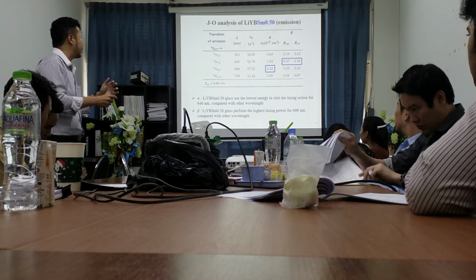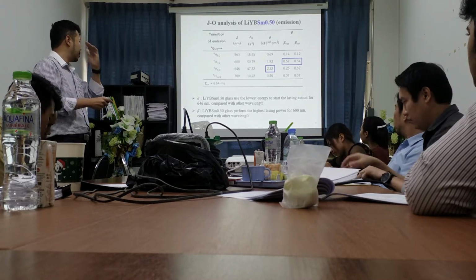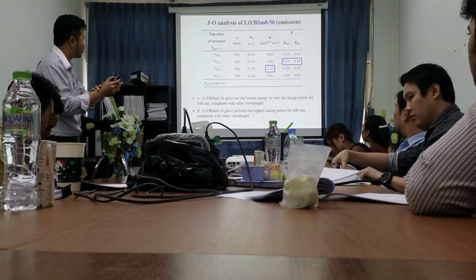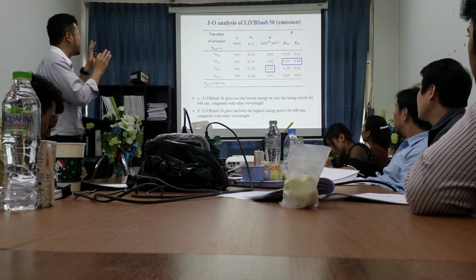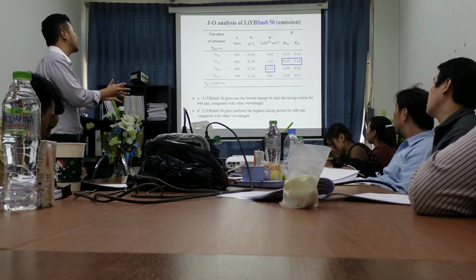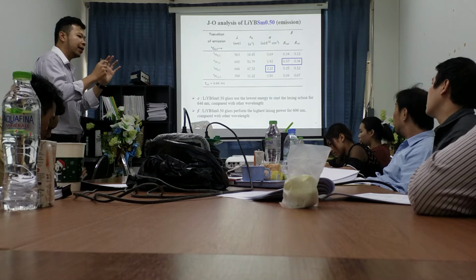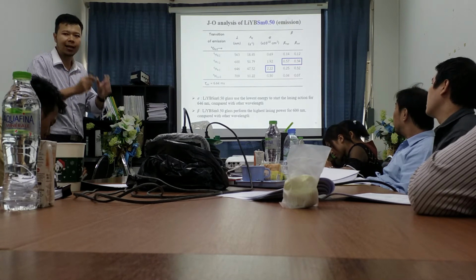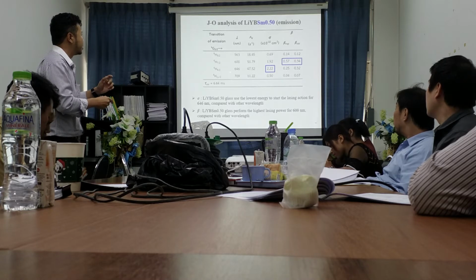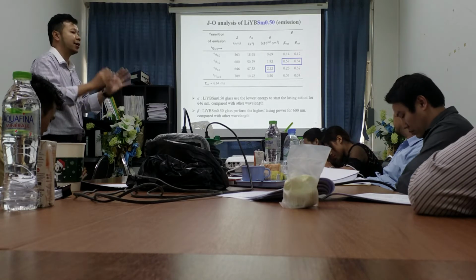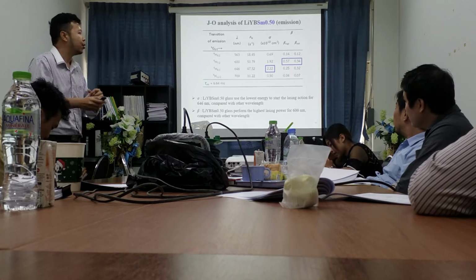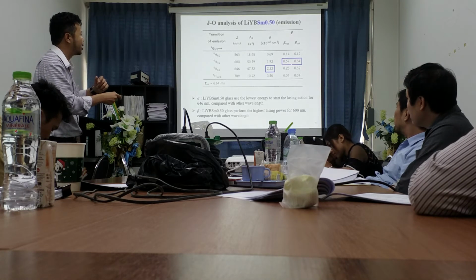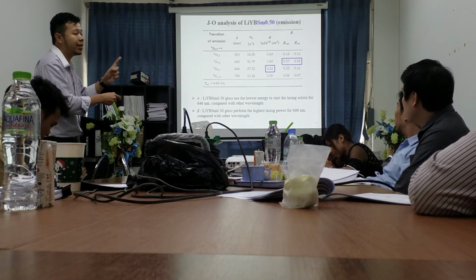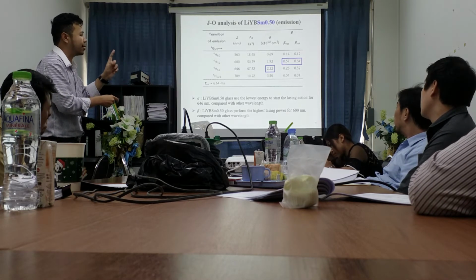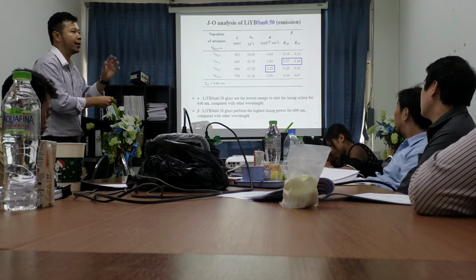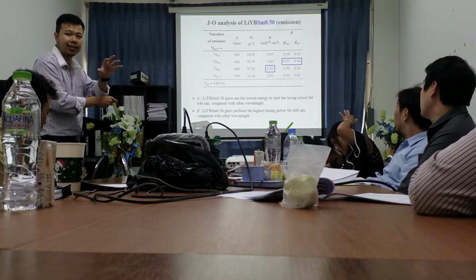The second step, we get the sigma and the beta, but we have a conflict between the sigma and beta values. From the discussion, we can say that if you want to use this glass for a low energy consumption laser, we need to use the 644 nanometer. But if we want a high power laser, we need to use the 600 nanometer because it shows the higher beta. Higher beta means higher power laser. Higher sigma means a lower laser threshold, the minimum energy that starts the laser action.